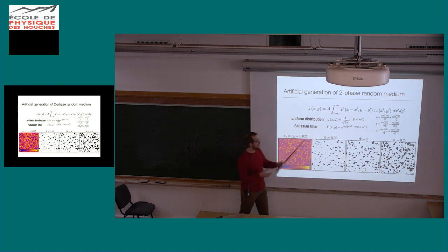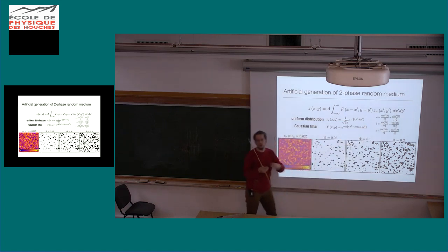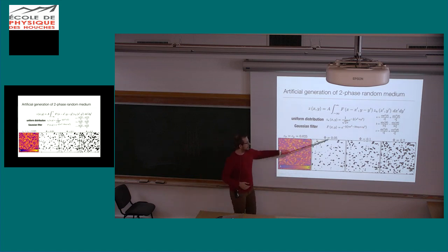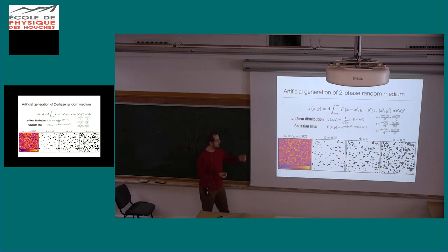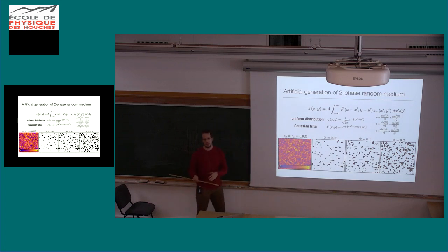With this, you can not only make something that is isotropic, so if those two are equal, but you can also make something that is anisotropic. And then I can just say, okay, I want 5%, 10%, or 20% of the weak phase, and then I just convert as many pixels above a certain height to that phase, and then I get structures like this. Those are not exactly the same structures that you see in an experiment, but those are the ones I decided to go with first.